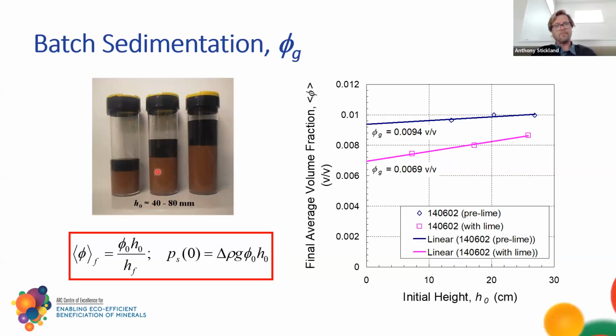This is for a red mud, which is from alumina processing. The particles are red, and the liquid, which is at a pH of 13, is caustic, dissolved up with a whole heap of alumina. The particles are red and have settled. And as you can see, as I go to the higher and higher initial heights, the proportion of the sediment to the overall height is decreasing. That's because the sediment is compressing under its own weight.